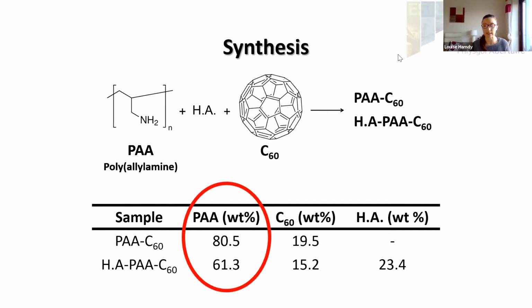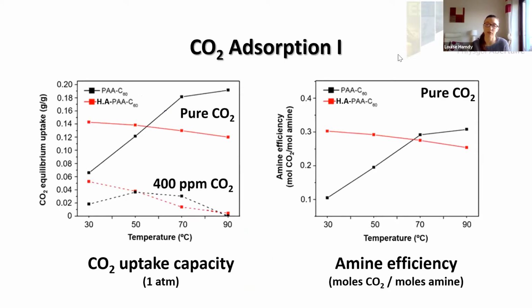Generally, in CO2 adsorption, because adsorption is an exothermic process, it's better at lower temperatures. However, with many polyamine adsorbents, we see that actually the adsorption is better at higher temperatures. This is because the increase in temperature affords the better thermal motion of the polyamine chains and opens up diffusion pathways so the CO2 can enter the pores, come into contact with the amines. So let me show you the CO2 adsorption of these adsorbents.